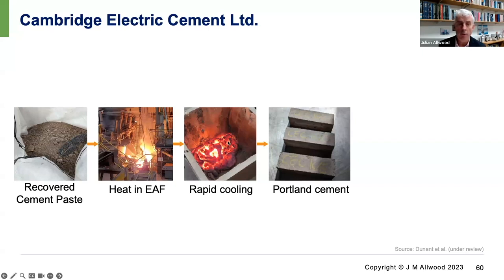And if we cool that rapidly in air and grind it, it turns out remarkably that it produces Portland cement. So in effect, this is a way of re-clinkering cement. It has no process emissions because the cement paste has already given up its process emissions in the first manufacture. And there's no additional energy input because the electric arc furnace was already processing a flux to make a slag that has no value as we stand.